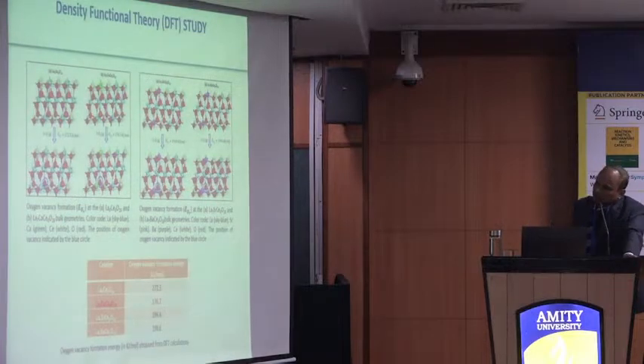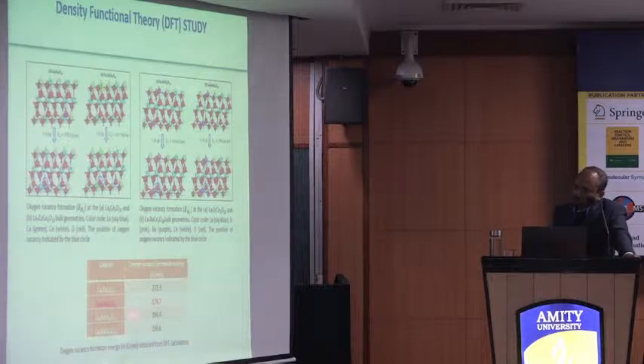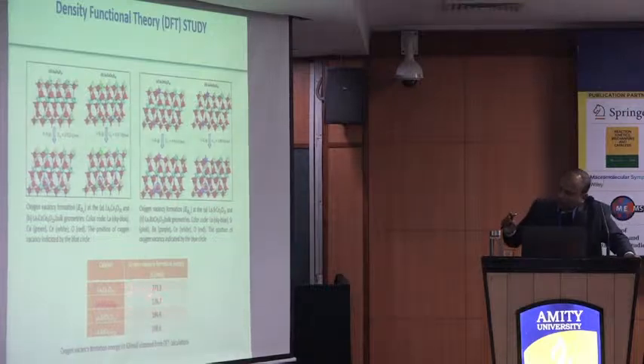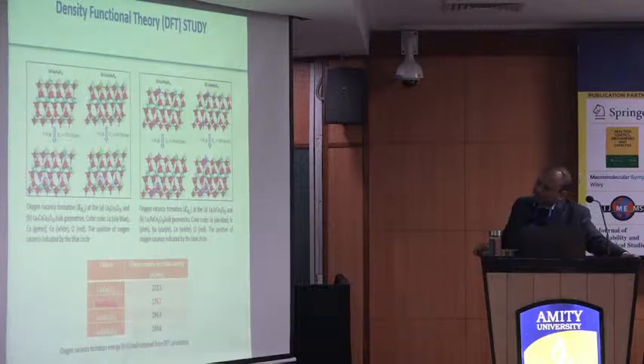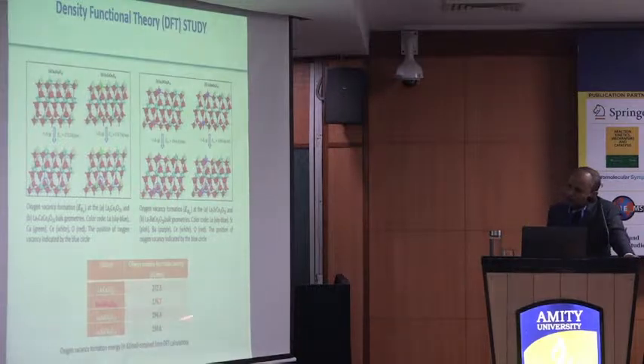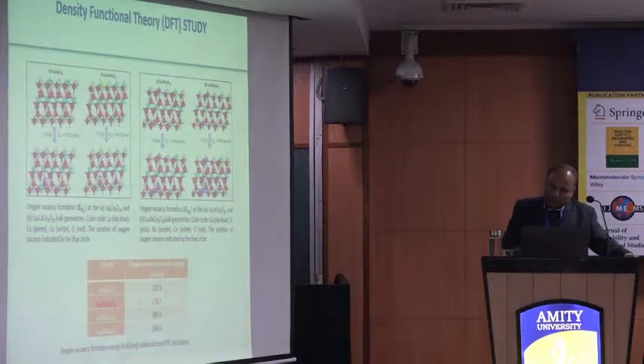Also, we have done some DFT calculation, and here we can see that the calcium supported lanthanum cerium oxide is active due to the presence of oxygen vacancy. You can see here the oxygen vacancy formation energy we have calculated, and this is the minimum for this catalyst. That means this catalyst is showing more activity for this methane to olefins reaction.